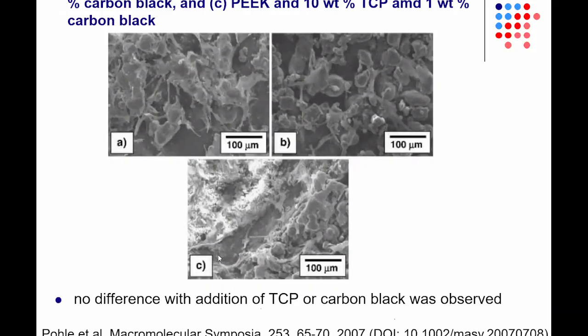So here you can see some details on the human osteoblasts grown on polyether ether ketone, PEEK with 1% carbon black, PEEK with 10% tricalcium phosphate and 1% carbon black. And you can actually see a little bit on how these structures can be used for osteoblast growth studies, bone cell-like growth studies, and essentially you can see that you do have good coverage.